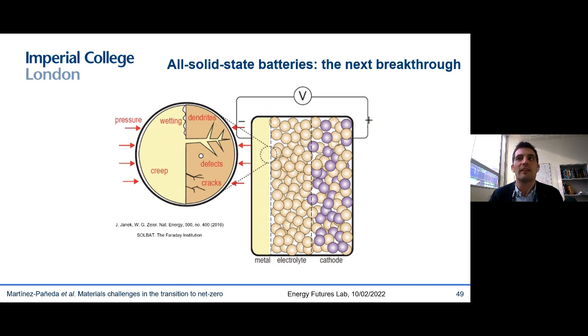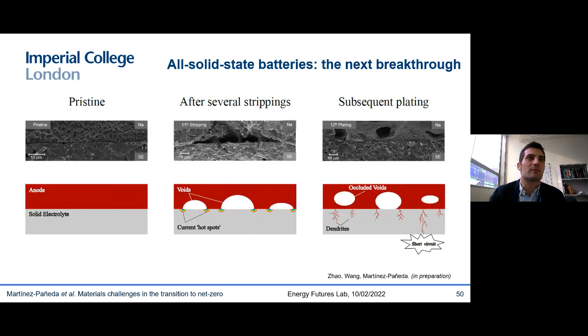However, this breakthrough is being hindered by mechanical interfacial instabilities. You can see some of them here. Basically, these instabilities occur at the Li-metal anode electrolyte interface and lead to cell death and the short circuit of the battery. In particular, the biggest problem one could argue is the presence of dendrites. So you have these dendrites here, these filaments that originate at the interface between the lithium metal and the electrolyte, and then propagate, reaching the cathode, short-circuiting the battery.